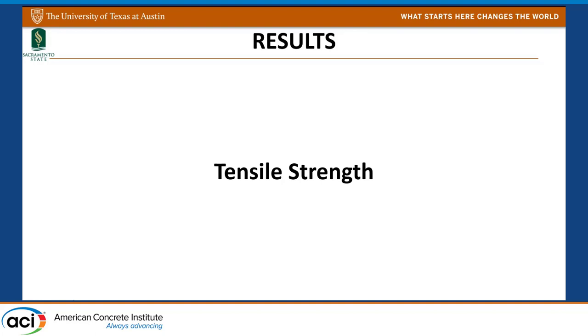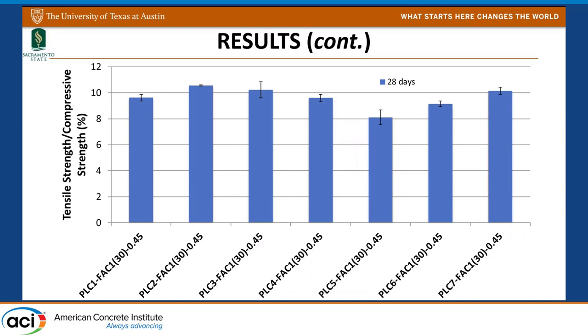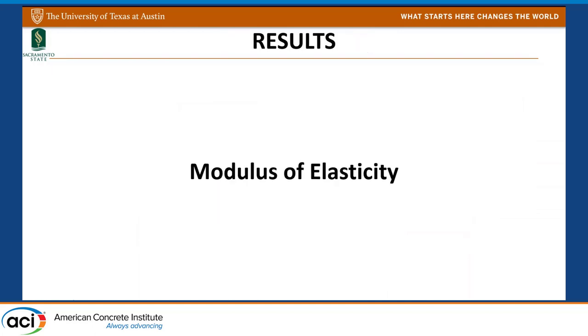We were also interested in the tensile-strength-to-compressive-strength ratio. We all know that for regular concrete we can expect about 10 percent tensile strength, and we wondered if that would hold true for PLC concrete. The answer was: for the most part, yes. With increasing limestone content we actually observed an increase in that ratio. When SCMs are added you get a little more variation, but you're still within the 8 to 12 percent range we would expect.